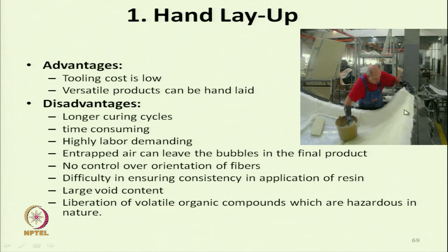The tooling cost is low with no specialized machinery required, and versatile products can be hand laid. The main disadvantages are a long curing cycle — time must be allowed for the matrix to solidify — and it is time-consuming. High labour demand is required because the matrix is poured and penetrated by hand. There are chances of air bubbles in the final product and no control over the orientation of fibres.